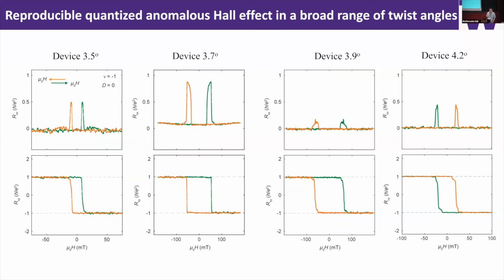One nice thing about twisted TMD is that the phenomenon is highly repeatable. As I talked about at the beginning, in graphene systems or other 2D material systems that realize quantum anomalous Hall states, the quantized Hall effect is not easy to repeat. But this is not the case for twisted TMDs. So far, we already have maybe 15 to 20 samples showing a very robust quantized Hall effect.